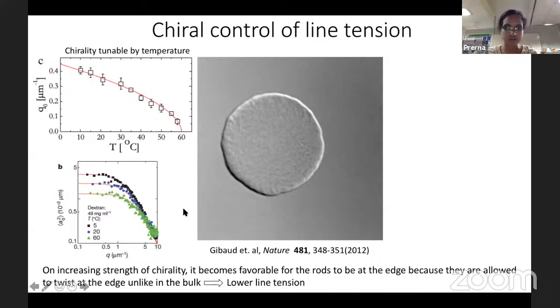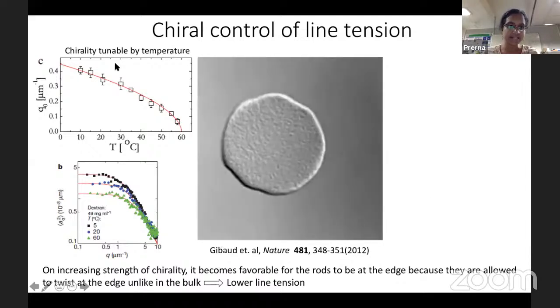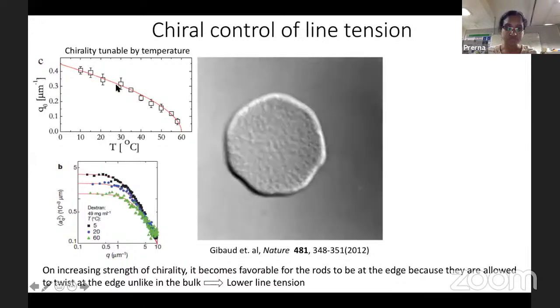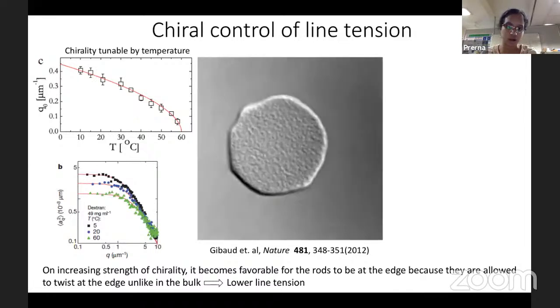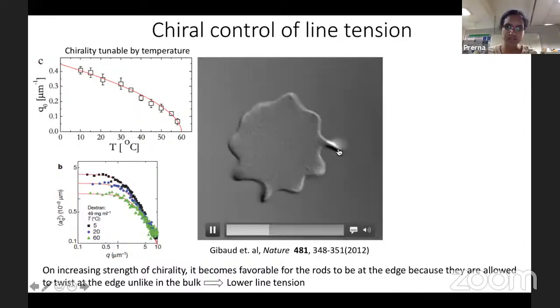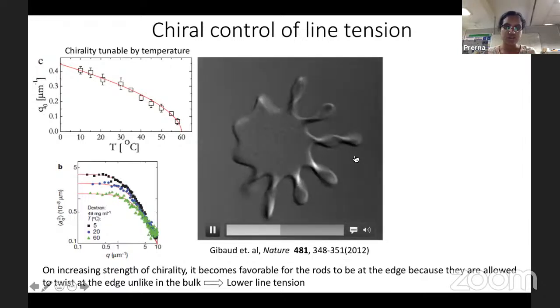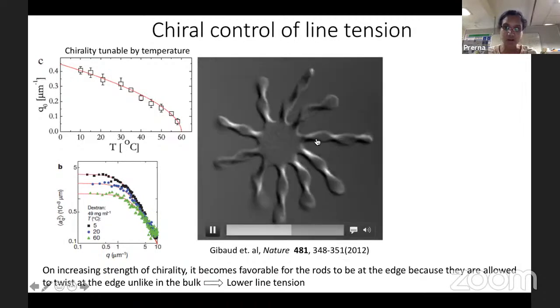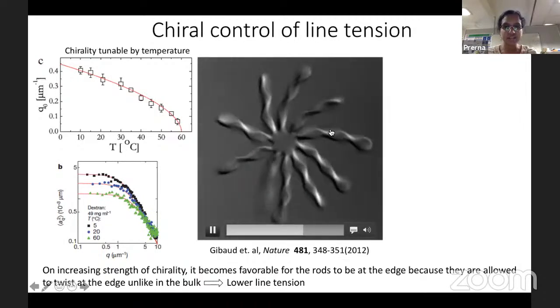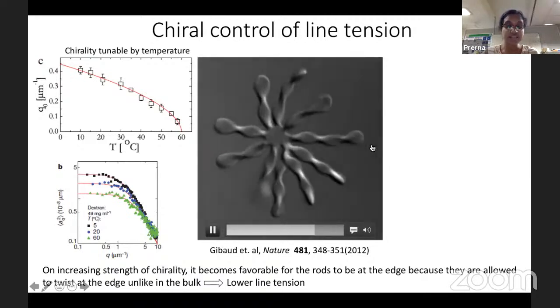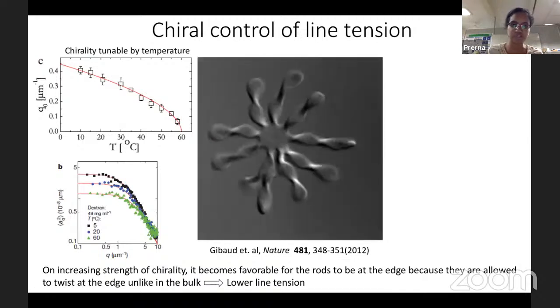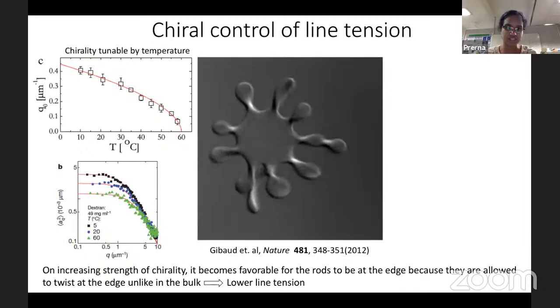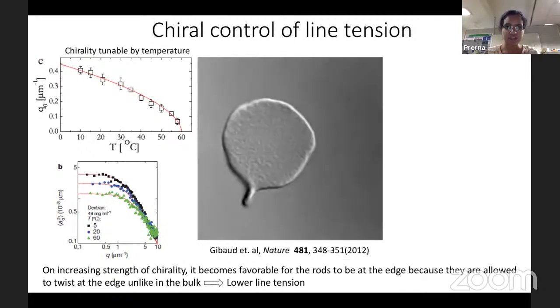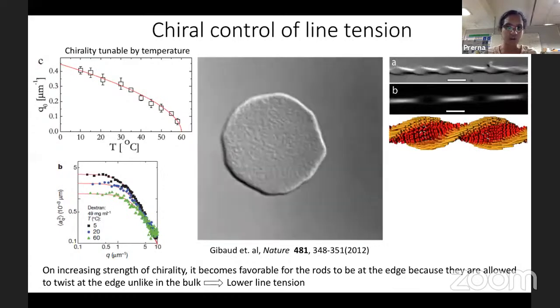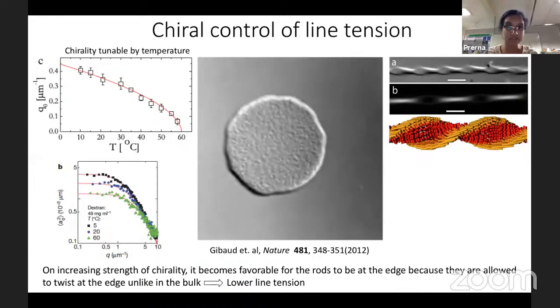So in this movie, I have a colloidal membrane whose temperature we will lower. And when you lower the temperature, chirality really dominates, and depletion loses out. So essentially now the edge becomes unstable, and you get these ribbon-like objects, linear objects where you can get lots of edge, and the rods can satisfy the chiral interaction. And this transition is completely reversible. If you go back to room temperature, it's going to come back to this high line tension state and become a circle, right? So that is one example of how chirality can control the line tension of colloidal membranes.